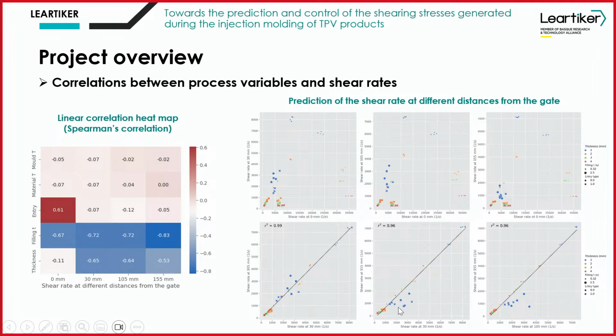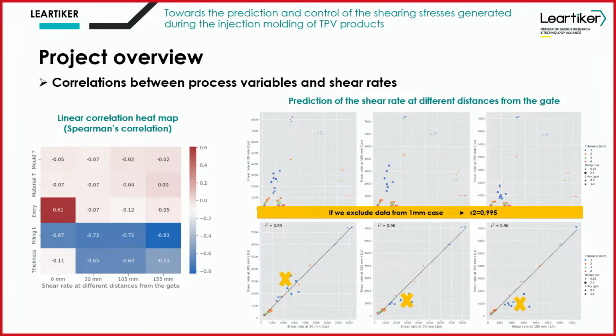Okay, you would say to me, but here you have some points that are not well correlated. So these ones are the ones related with the 1 millimeter case, but as I previously discussed, the 1 millimeter case is the one that deviates a bit from the rest, and if we exclude the 1 millimeter and only use the 2, 3, and 4, in this case, we get a very good linear correlation between the shear rates at the different positions. So this is very interesting, because we are able to correlate the process parameters with the shear rate, and we can simulate or predict this by only simulating one point, not performing, as we have done, 64 simulations, but fewer simulations in only one point of the plate.